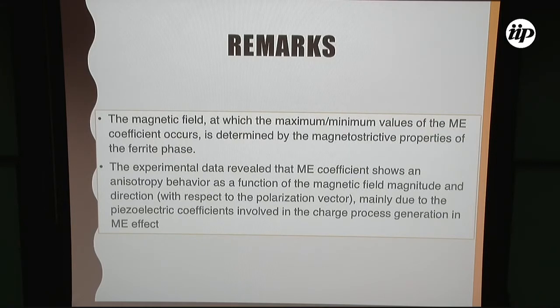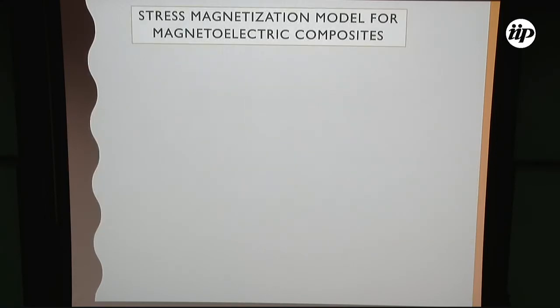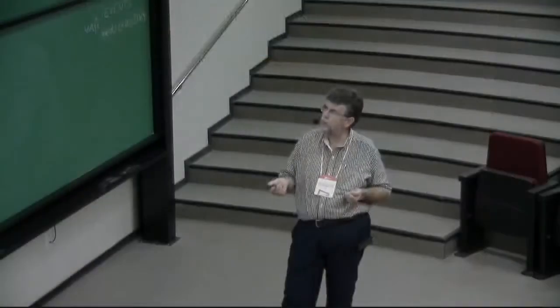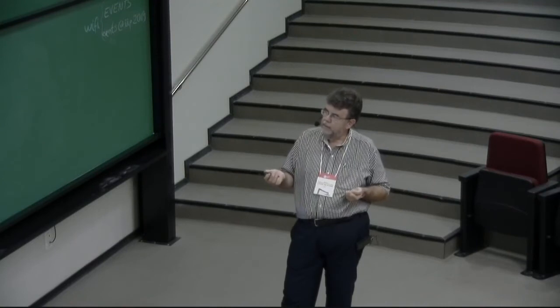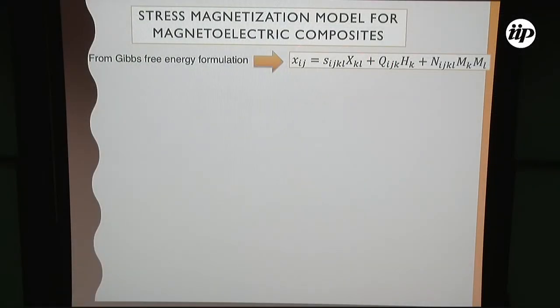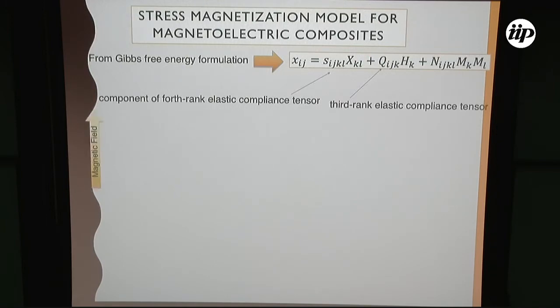the study of the effects of low temperatures on these properties. From the Gibbs energy formulation, it's possible to explain this tensor as a function of the magnetization, the piezomagnetic coefficient and the strain of the sample. It's possible to explain magnetostriction as a function of this tensor.